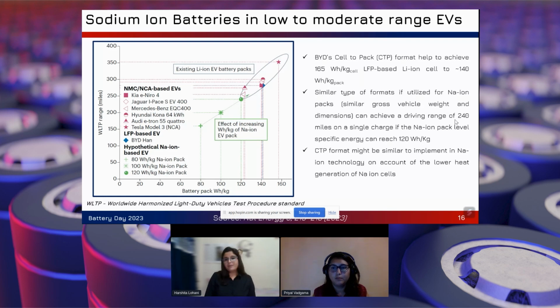And BYD has actually used the cell to pack format to achieve this 140 watt hour per kg at the pack level from a 165 watt hour per kg at the cell level LFP based lithium ion cell. And if a similar type of format, similar battery pack engineering could be done for sodium ion cells as well, then these batteries can also achieve a very good mile range, which is especially advantageous for low to moderate range electric vehicles. This cell to pack level reduced a lot of inactive material present in the battery pack. They are going directly from the cell level to the pack level, eliminating the module formation in between. Because of that, they are making long cells, around 600 mm long, and directly placing them to make the battery packs.